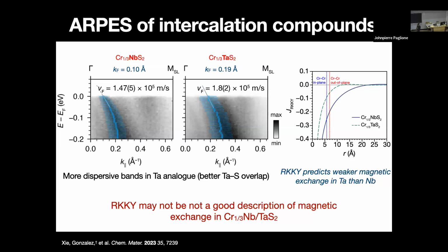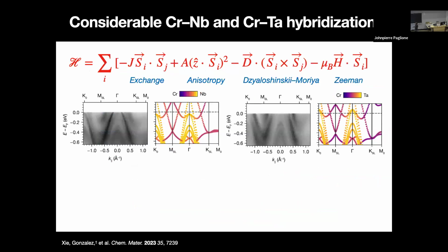And so this starts to suggest that maybe we shouldn't just assume that RKKY is the dominant or the operative magnetic exchange interaction. And in fact, that kind of makes sense, because if you follow that up with some calculations, you find that there is extensive hybridization between the intercalant and the host lattice atoms. RKKY relies on these localized moments connected to itinerant electrons, and really assumes that the host lattice bands are rigid and not being influenced fundamentally by that magnetic dopant ion.